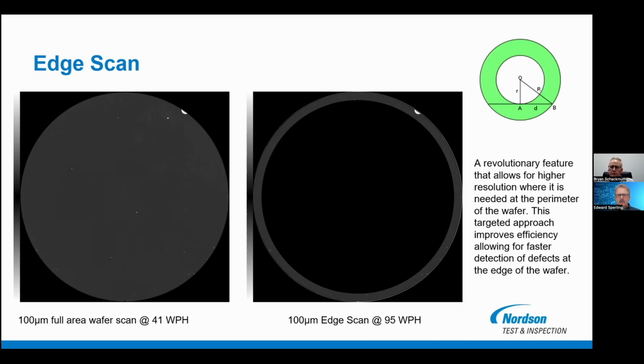The reason customers are interested in that is the CTE, or coefficient of thermal expansion, changes across the different materials in the wafer. That effect is greatest at the edges. When we were looking at standard flip chips, that was always the perimeter solder bumps. Same story here in wafers, it's that edge. And so what we can do is scan that edge at a higher resolution to see finer detail. And then maybe we scan the center area, which is a bit easier to bond, at a lower resolution. So we can really optimize the scan time around the customer's requirements.